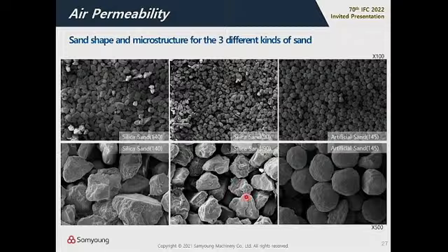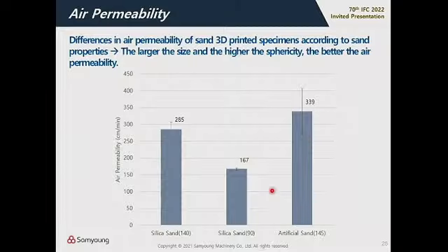And these are the pictures of the microstructure for the 3 different kinds of sand. As you can see, the sphericity of the natural sand, these 2 are natural sand, looks not that good, but that of the artificial sand looks good. And this is the test result. This is the result of silica sand 140, this is for silica sand 90, and this is the result for the artificial sand 145. It shows that the larger the size and the higher the sphericity, the better the air permeability.